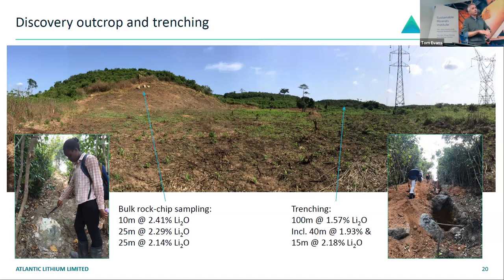And that was all down to the fact that we were sampling weathered material and relatively small samples from a rock chip point of view. These are quite coarse grains, so you've got that nugget effect essentially to look out for when you're taking rock chips. So when we found out that lithium was very mobile, and certainly in this latitude, we went back to those areas and actually dug deeper in our trenches, resampled larger samples, and bang, reported these results. So from going from 0.1, 0.2% lithium oxide and nearly walking away from the project in 2016, 17, we announced these maiden results.